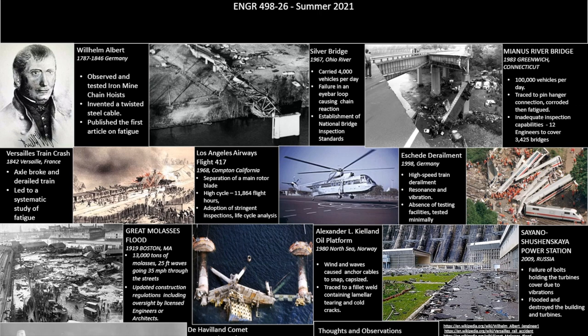Below that, the Eschede derailment occurred in 1998 in Germany. A high-speed train derailed, killing 101 people and injuring 88. It was caused by a single fatigue crack failure, which locked the wheels of the train into a different path than intended at a junction point. The train attempted to go down two different tracks. Fatigue failure occurred as a result of resonance and severe vibrations. Fatigue was further exacerbated by the plastic deformation or flattening of wheels during revolution. No facilities at the time existed to be able to test the failure limits of this wheel.